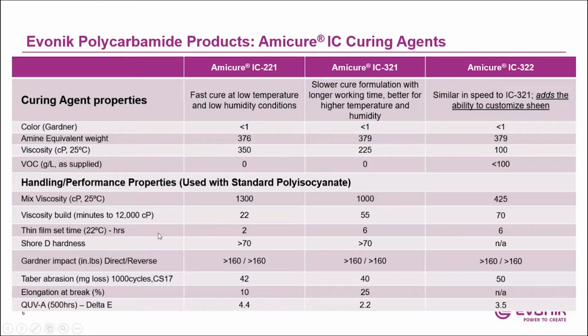Thin film set time, that's the important property here. So how fast does it cure? What we talked about in terms of cure time is really at ambient conditions, 22 Celsius, 50% relative humidity, and 221 has about a 2-hour cure time. 321 and 322 have about 6 hours. I will discuss a little bit more in terms of what happens at lower temperature, higher humidity later in the presentation. The Shore D hardness values are generally, these are hard coatings, so greater than 70 Shore D.